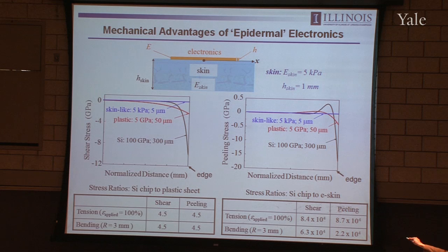And you can compare calculations for silicon chip, sheet of plastic, and skin-like construction. What you find is that when you enter this low modulus simultaneously with low thickness regime, you drive those interface stresses down to very close to 0. Factor of 1,000,000 smaller than what you have to struggle with if you try to bond a silicon chip to the skin. And so that becomes a very, very powerful feature of the mechanics, and it really drives the design of the electronics into this sort of epidermal modulus matched regime.